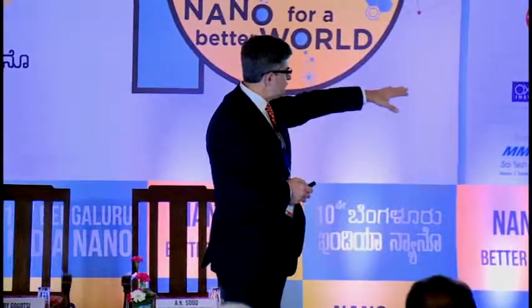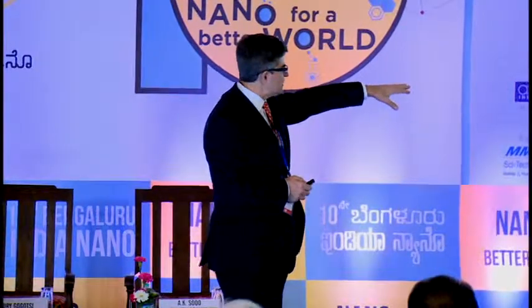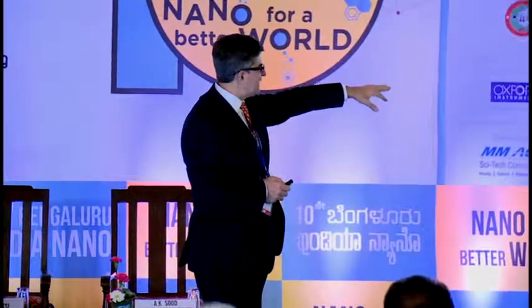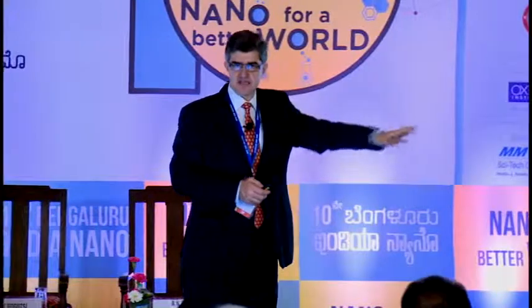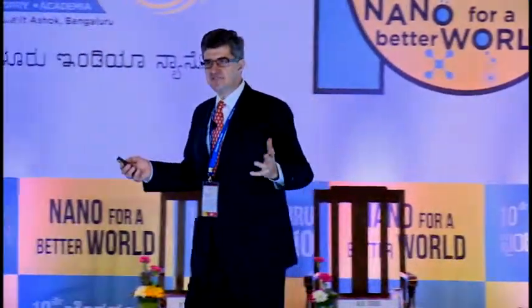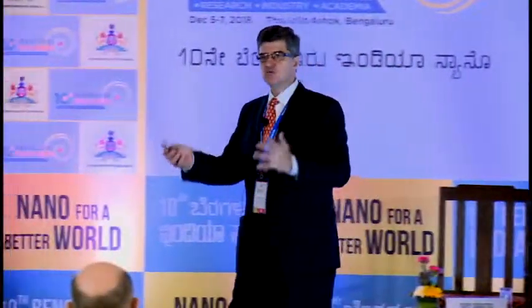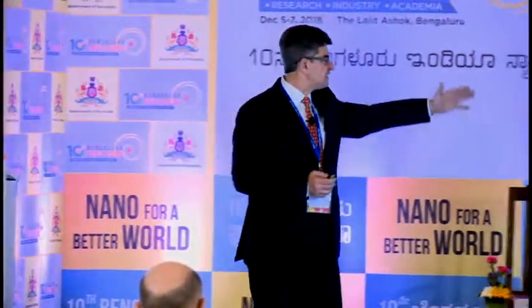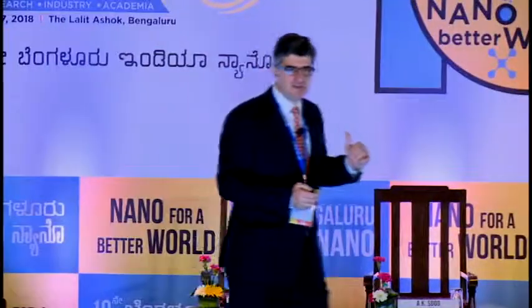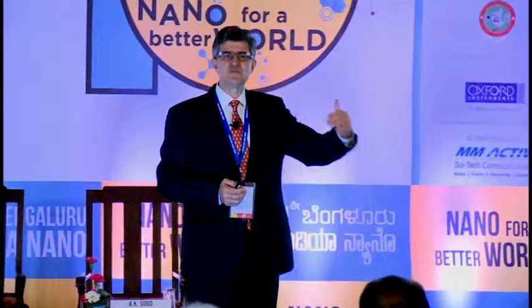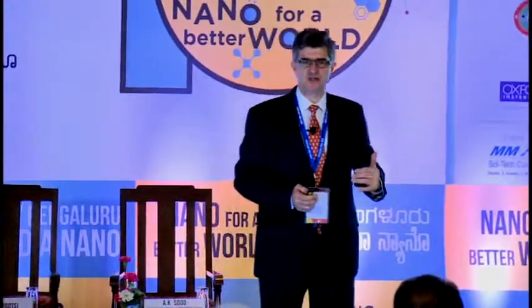But what you can notice here, we can go to about 100 volts per second. A supercapacitor is considered to be a very fast device when charged at between 10 and 100 millivolts per second. Here we can go to 100,000 millivolts per second, and a month ago we published a paper showing we can go actually to 1,000 volts per second charge-discharge here.